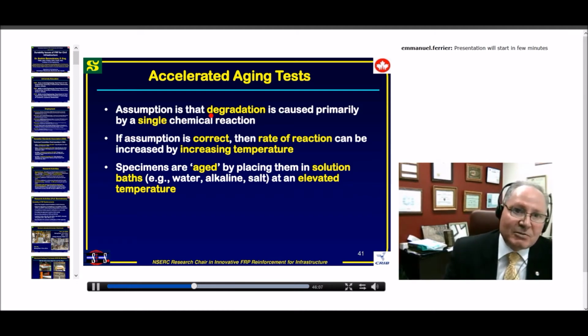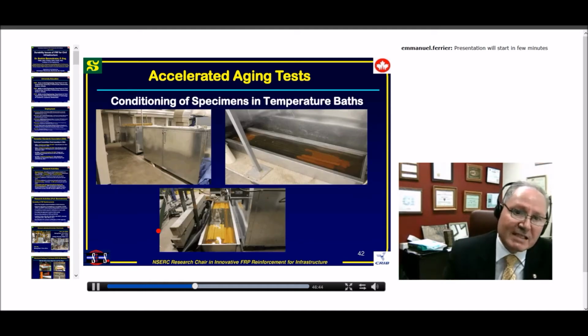But there is an assumption that degradation is caused primarily by a single chemical reaction. Otherwise, if you have two or three, of course, you cannot use accelerated aging tests. If the assumption is correct, then the rate of reaction can be increased by increasing temperature, and specimens are aged by placing them in a solution bath as we are doing. We believe strongly that our degradation is mainly coming from chemical reaction. It could be from the resin, mainly from the interface, or from the fiber, as I explained before. I will explain later, when we draw the results and curves, we can see whether this assumption is fulfilled or not.